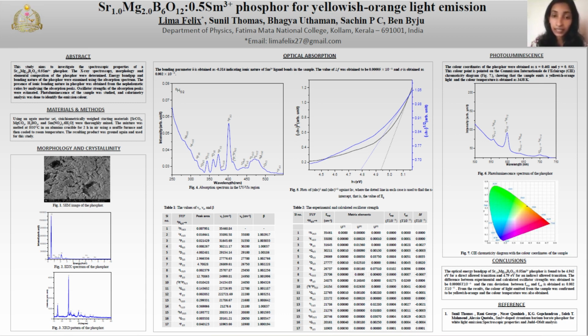The CIE 1931 xy chromaticity diagram is used for the two-dimensional graphing of color independent of lightness. x and y are the chromaticity coordinates calculated from the tristimulus values XYZ. In this diagram, the achromatic colors are towards the center and chromaticity increases toward the edges. The color coordinates of the phosphor were obtained as x equals 0.461 and y equals 0.532. This color point is plotted on the CIE chromaticity diagram as shown in figure 7, showing that the sample emits a yellowish-orange light, and the color temperature is obtained as 3438 Kelvin.